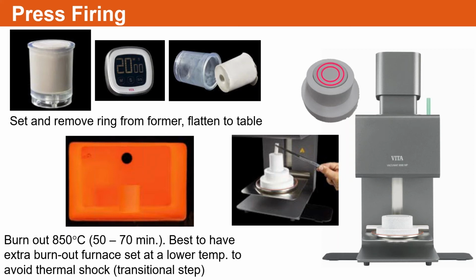And you don't want to put a cold ring in a hot burnout furnace. So if you're not paying attention to the setup time and to placing the ring in your burnout furnace at the appropriate time and temperature, you end up maybe shocking the investment, going from a colder area to a very hot burnout furnace, 700 degrees, 850 degrees Celsius. When you reach in and grab your ring from your burnout furnace, you will actually see it radiates a bunch of micro fractures.